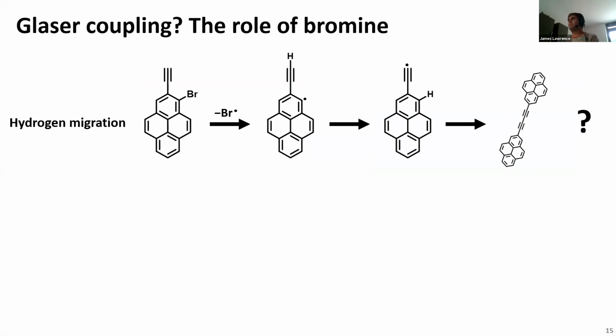So there's a couple of different potential options for what role the bromine actually plays. It can be that when you heat this precursor with bromine on the surface, the bromine comes off and leaves behind a radical, and you get some sort of maybe surface-mediated hydrogen migration from the end of the alkyne to the side of the molecule, leaving behind a radical on the end of the alkyne, which can then go and form this Glaser coupled structure. An important aspect of this is that if you try to do this without forming a radical here, without a bromine, I think this has been shown to be endothermic in theoretical calculations of another molecule on, I think, a silver surface. So in this case, because we have no net loss of hydrogen, it's actually exothermic. So it's just like losing a bromine, basically.